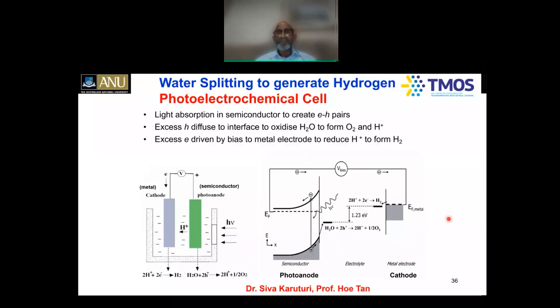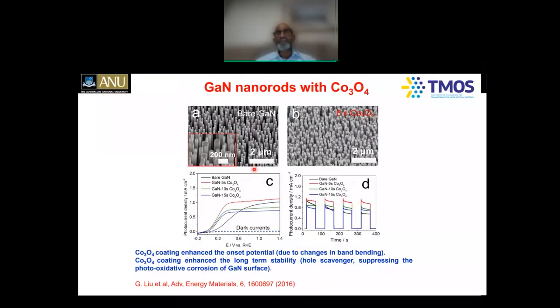One of the challenges has been these semiconductors: either they're efficient but not stable, or they're stable but not efficient. So we are really trying to find materials which are stable and efficient. We've been looking at gallium nitride nanorods, which are made by the top-down approach. This is the work of my student, Dr. Reddy, who is now in engineering, and also Dr. Liu, a young colleague from engineering. Gallium nitride is very difficult to etch normally. But despite the normal stability of gallium nitride, we have shown in this case that photo oxidation takes place and it's not stable anymore.